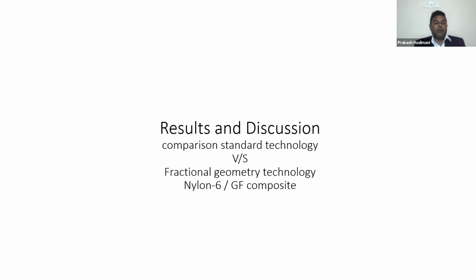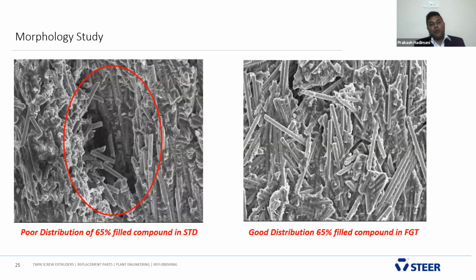Nylon 6, we know, is a semi-crystalline polymer and hygroscopic in nature. Currently, everybody is going for a 20% to 50% fill of glass fiber. Addition of glass fiber increases the viscosity and reduces the shrinkage factor. If we see here, the trial was conducted with addition of glass fiber beyond 50%. Beyond 50% addition of glass fiber is challenging. Again, wetting of the glass fiber is a big challenge. The nylon 6 has to completely coat onto the glass fiber. That is the biggest challenge.